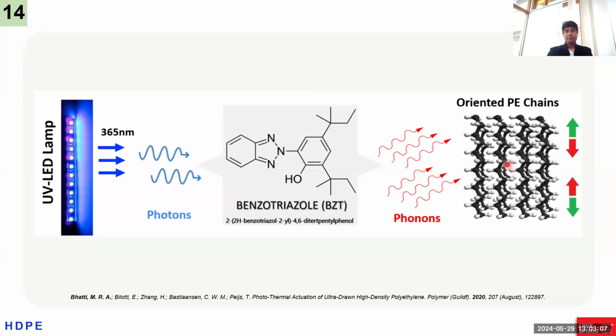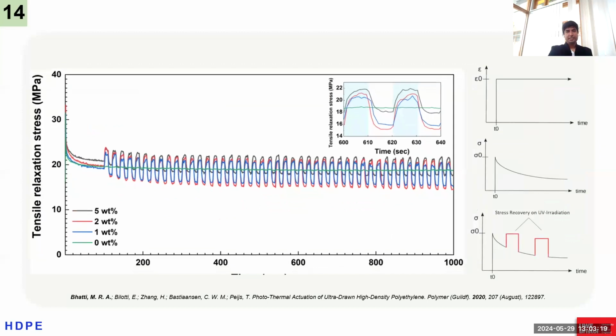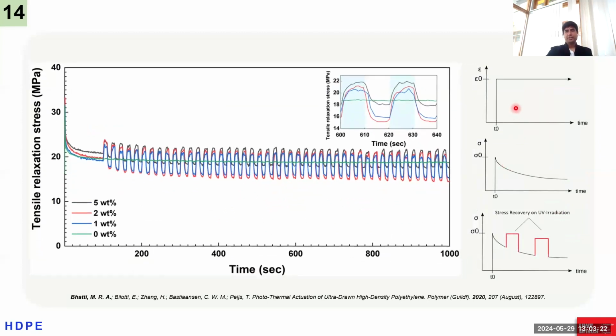And if we clamp these films in a tensile tester, restraining them from contracting, the response will be in terms of actuation stress. So we devised a simple experiment of tensile relaxation. In that experiment, the strain is kept at a constant level. And because of the viscoelastic nature of polyethylene, the material tends to relax in terms of tensile stress. But when these films containing BZT are illuminated with UV light, they respond in terms of actuation stress upon UV radiation. As you can observe over here,